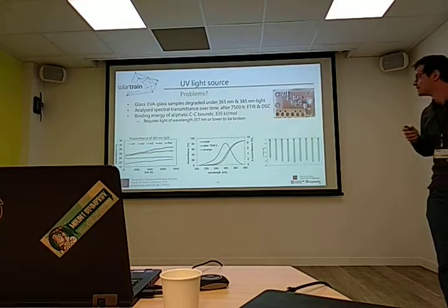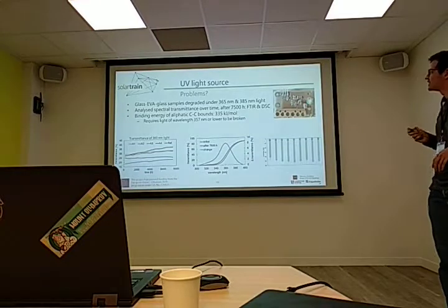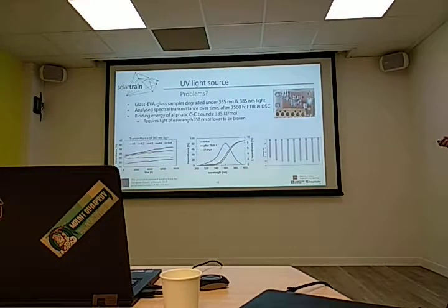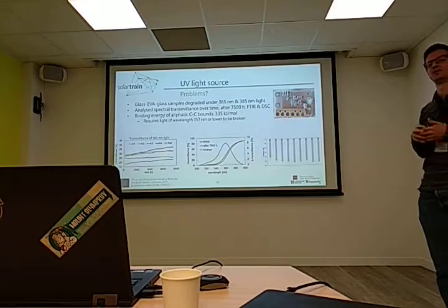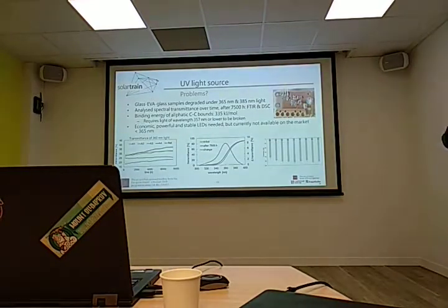It was surprising to me, because there are aliphatic C-C bonds in the material, and the wavelength for them to be broken is 357 nanometers. So if we are above this wavelength, light just doesn't have the energy to do any serious chemical degradation of the material. So to really do good degradation experiments with LEDs, we need more economic, more stable, and more powerful LEDs.